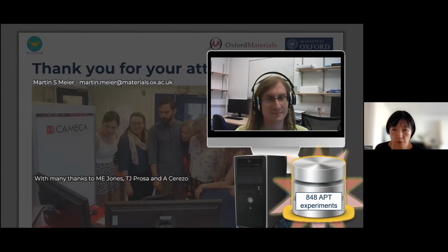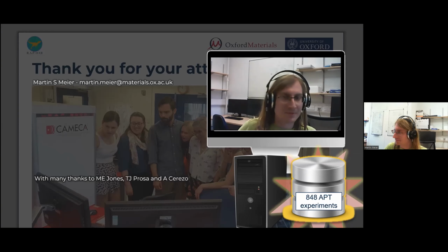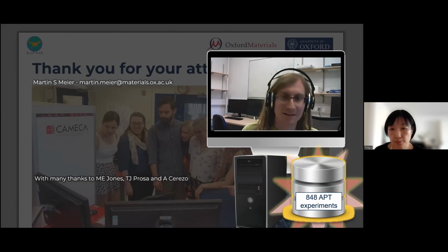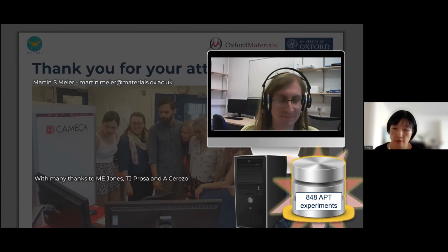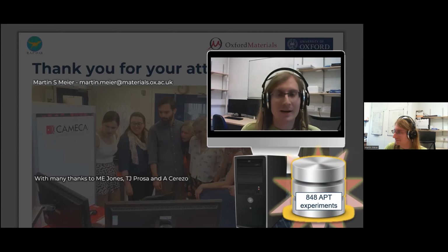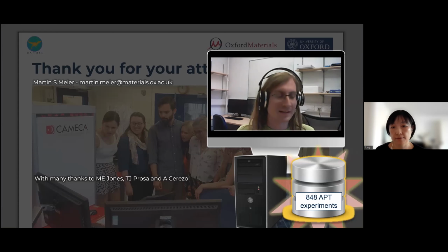I'm wondering, you were talking about these zirconium H complex molecules, for say hydrogen zirconium. Is this zirconium hydrogen really initially bonded in the material, or is it, as you said, the association and recombination of zirconium and hydrogen, and do you think you can use the energy deficit to distinguish this effect? Sorry, I think your sound quality on my side is quite low. What I mean is about the zirconium H peak. Do you feel this is really from the material, with zirconium bonded to hydrogen, or is this something you can differentiate from the energy deficit? In fact, is there some recombination process during evaporation?